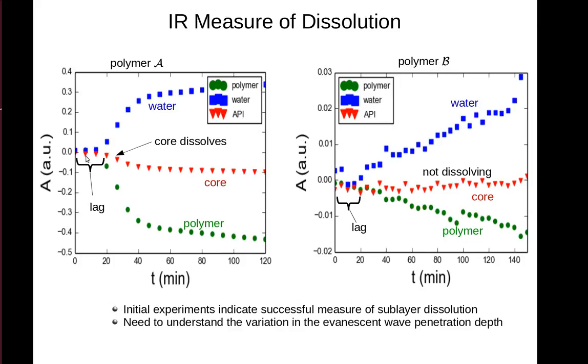Looking on the left, the beginning of the experiment again, there's initial lag as the water penetrates through the layers to get to the crystal surface. Then we see the water intensity growing in. We see the polymer being dissolved and its intensity decreasing.